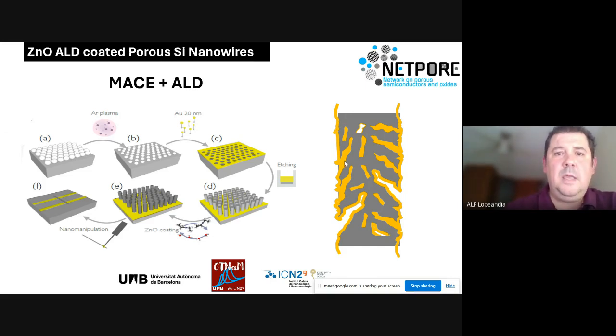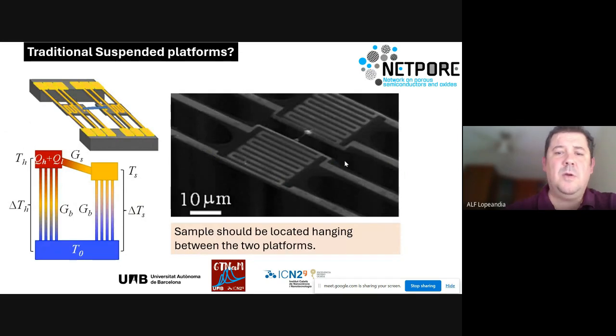And then, as I said, we already had some platforms, what we call the traditional suspended platforms, where we have two meanders. This is a 20 by 20 micron platform, more or less, that is separated a few microns from each other, and we hang the wire in between them. We attach it, as I will show in some pictures later, with a focused ion beam. We do the deposition of the platinum, of the polymeric based platinum, and we hang the nanowire in between them.